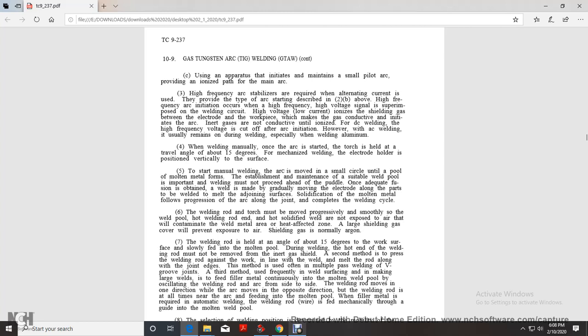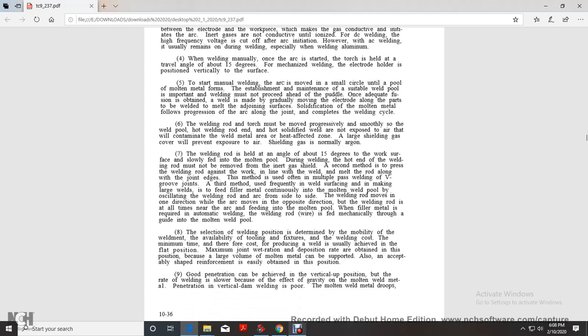The welding rod and torch must be moved smoothly so that the welding pool, the hot welding rod, and the hot solidified weld are not exposed to the air. They will contaminate the weld metal and heat affected zone. A large shielding gas cover will prevent exposure to the air. Shielding gas is normally argon.